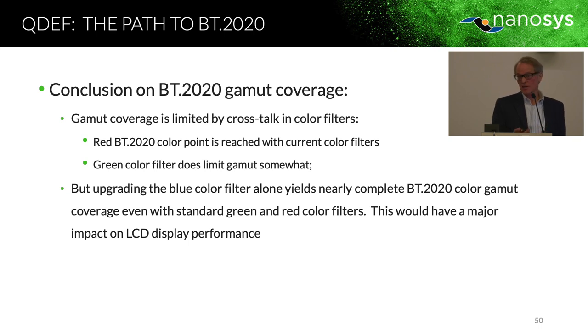So the green filter does limit gamut somewhat. We didn't get to 100% gamut coverage. There is some problem with the green channel. The red is pretty much where it needs to be. Obviously, making it narrower allows you to move it more into where the eye is sensitive, which is desirable for brightness. But the blue filter is the biggest contributor to gamut erosion.